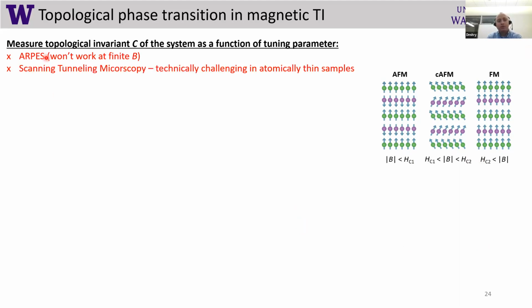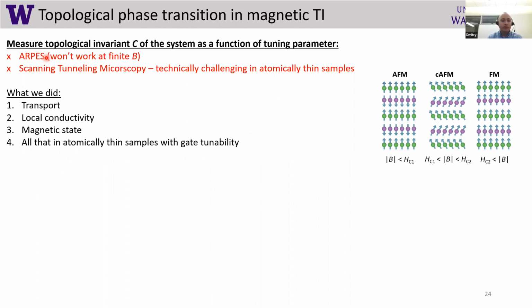So as I said, there are three main states: antiferromagnetic, canted antiferromagnetic, and ferromagnetic, depending on external magnetic field. And we were looking at how we can essentially map out and understand topology in each of these cases. So as soon as we need external magnetic field, ARPES is very difficult, and essentially, it won't work. STM is also technically challenging because in our case, we also want to change Fermi level and observe what's happening at different gating. So STM was also basically tricky, and I don't think that anybody developed STM of gate tunable MBT yet. So what we did instead, we used transport, local conductivity and magnetic state measurement to essentially understand how all this topology and magnetism interact with each other.